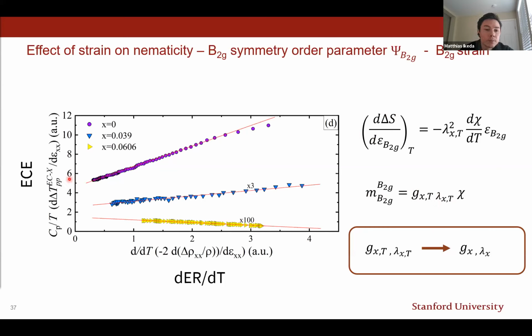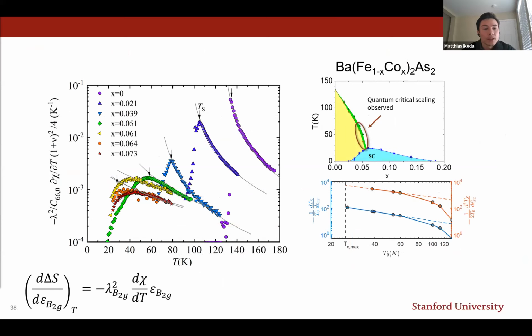And this is what is shown in the figure on the left-hand side for various compositions across the phase diagram of cobalt-doped barium 122. So we can see that indeed G and lambda do not exhibit strong temperature dependence in this system. Coming back to the elastocaloric effect, again, we measured as a function of cobalt concentration, and the data is shown here in the figure on the left-hand side. So you can see that the magnitude of the elastocaloric effect indeed drops significantly as we increase the cobalt concentration. And assuming that dχ/dT is not strongly composition dependent, and such evidence was actually provided through Raman measurements, we already realize that in this system, the nematoelastic coupling constant must drop down significantly as we approach optimally doped regions in the phase diagram.